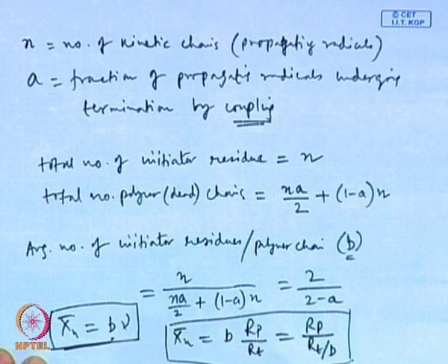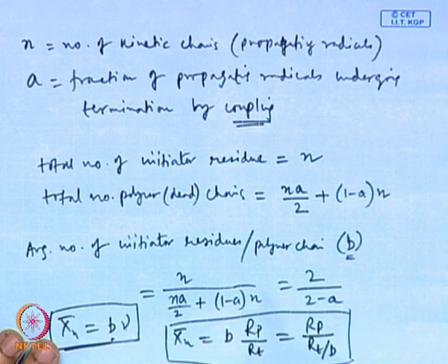So, this is the average number of initiator residues per polymer chain, we can get it from this. Unless the monomer is sterically crowded, if we are talking about a coupling reaction, then two radical chain ends have to come and collide with each other. Unless the monomers are sterically crowded or they have an easily abstractable beta hydrogen, in the majority of cases they undergo termination by coupling reaction, like styrene, acrylonitrile, methyl acrylate. They are not very sterically hindered,